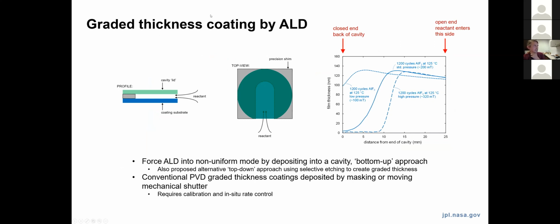When I described ALD initially, I described one of its key advantages as its extreme uniformity. So we had to do a bit of head scratching to figure out how to get non-uniform ALD films in order to maintain our existing infrastructure for coating these detectors and our existing processes and modeling. And the approach that we've adopted is this cavity approach, where we can force ALD into a non-uniform mode by limiting the spatial extent to which reactant can coat the substrate of interest, basically by putting a lid on the process. So here's a cross-section view of how this works.